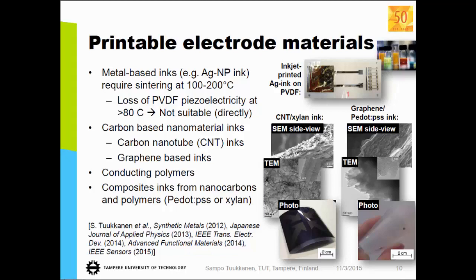So normally when you talk about printed electrode materials, you use the metallic nanoparticle inks. Like silver nanoparticle ink is mostly used, but that's quite expensive. But okay, people are trying different ones like nickel and copper, but there are some challenges in that area also. And normally these nanoparticle inks need some sintering, like from 100 to 200 Celsius, to melt the nanoparticles together to have a conducting film. So this is not suitable for our PVDF, which is then destroyed.